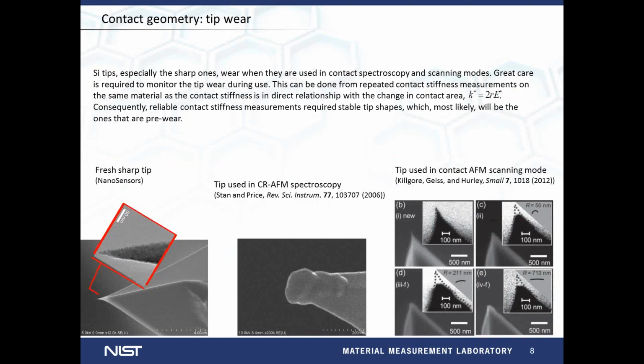Being a contact AFM mode, the tip condition requires a lot of attention during measurements, both in point measurements and scanning. A direct way to assess the tip wear is to image the tip before and after use, like by SEM or TEM, but this might not be available all the time. So an indirect way is to repeat the same contact stiffness measurements on a given material and observe if there are significant changes in the measured contact resonance frequencies, because these changes will indicate a change in the contact area solely.